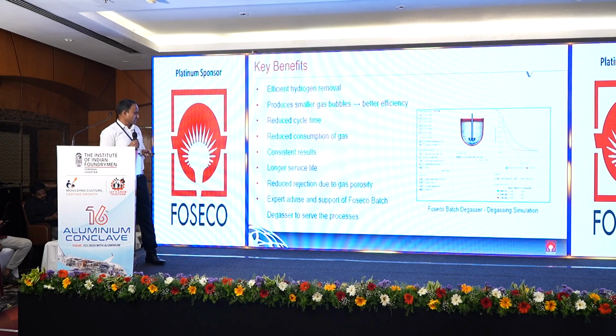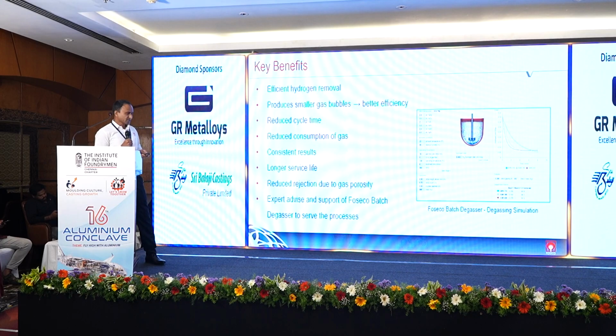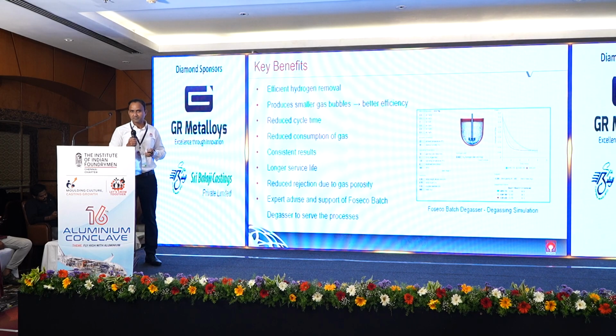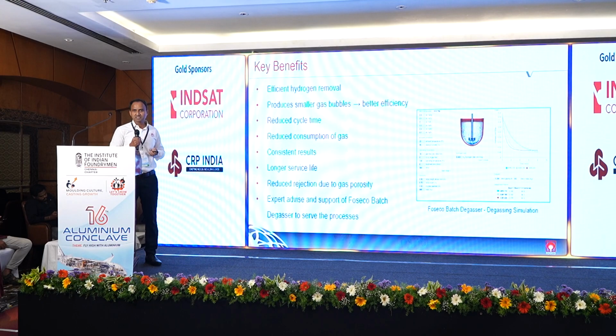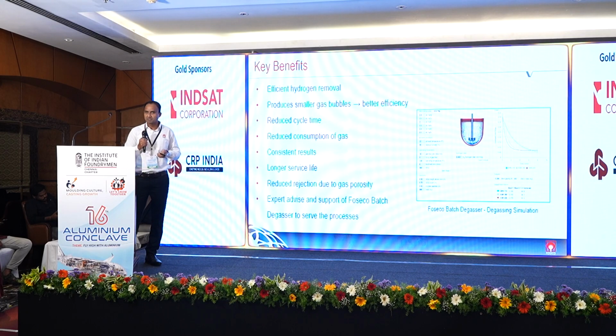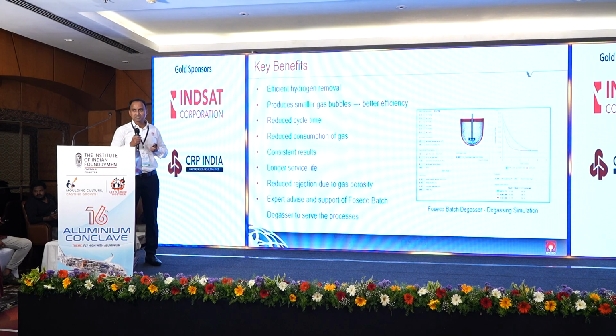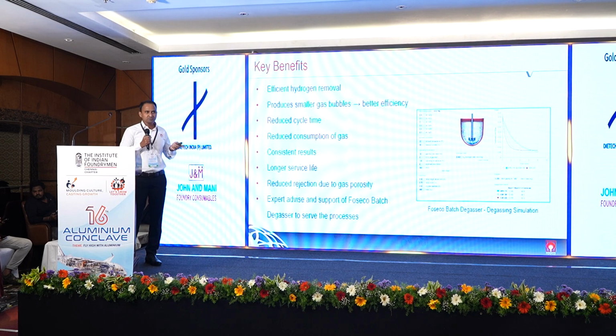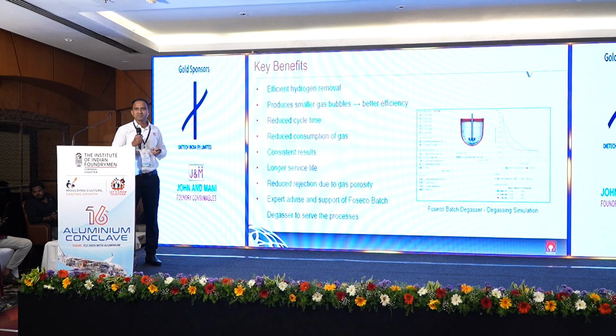Another benefit is that we have an expert international team, and Foseco has simulations like the Foseco batch degasser. With the help of batch degasser simulation, we can optimize the degassing cycles. Here we need some inputs like alloy type and ambient conditions like ambient temperature and humidity. Accordingly, we can set the process parameters, like how much gas to keep, 12 LPM or 15 LPM, depending on metal quantity and time, and also the volume of the crucible or ladle. With these inputs, we can set the parameters and achieve the density index in a shorter, optimum time.